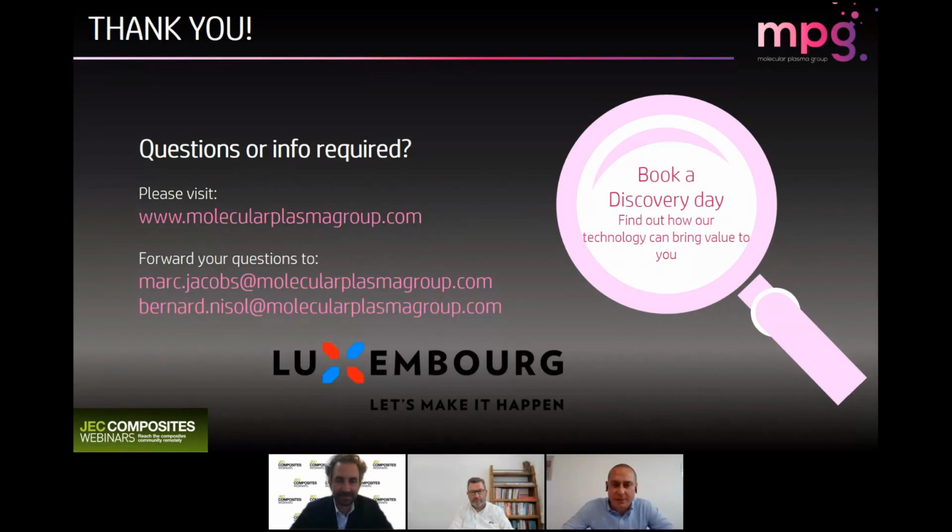So basically we're depositing nanometric layers. We will not fill the material. If you have a micrometric surface, you will be able to penetrate the pores and the irregularities at the surface, but you will only coat with a very thin nanometric layer, say 10 to 100 nanometers. So this is how we ensure a uniform coating, because we're in very different ranges: the roughness on one side is micrometric and the layer is nanometric.